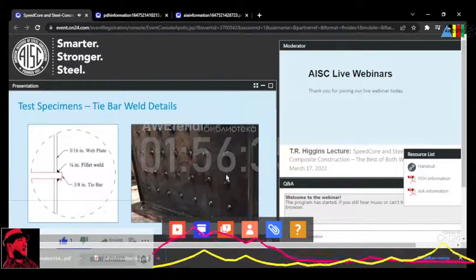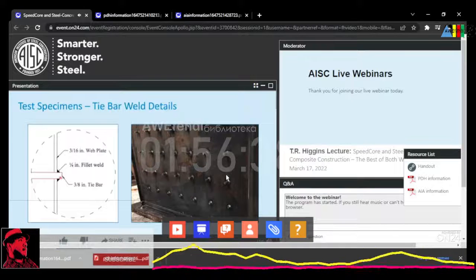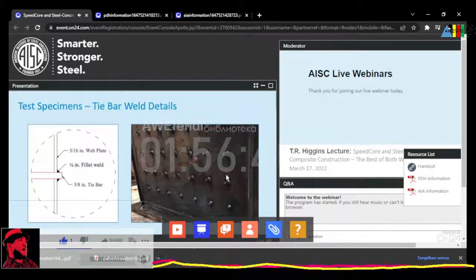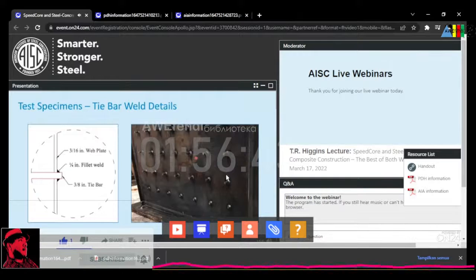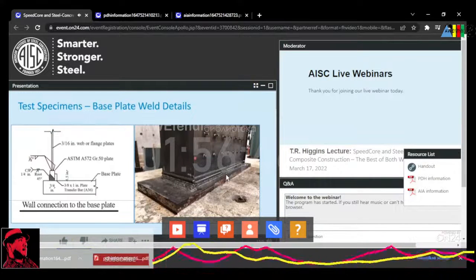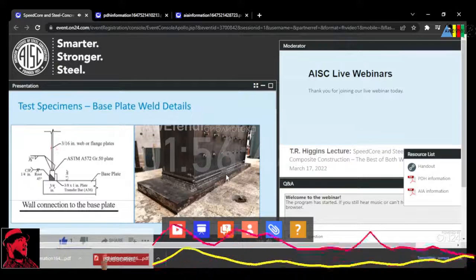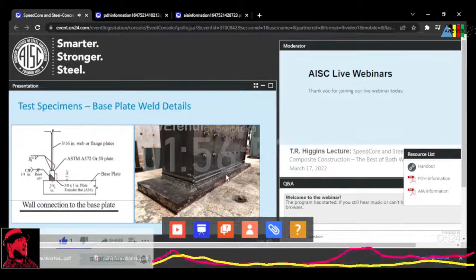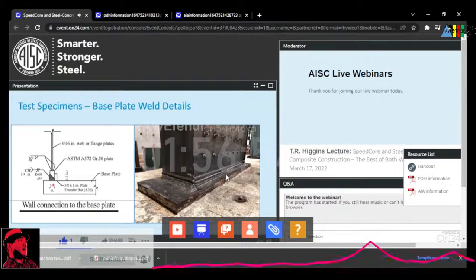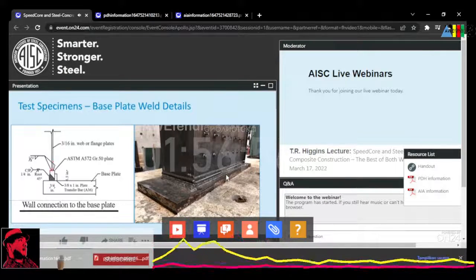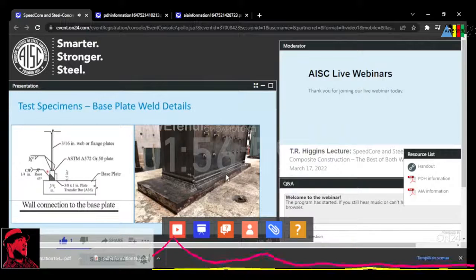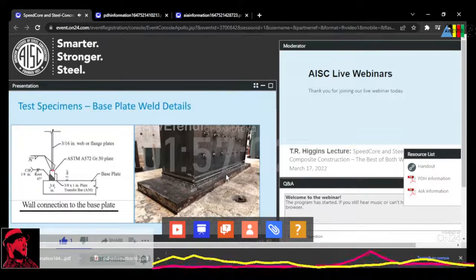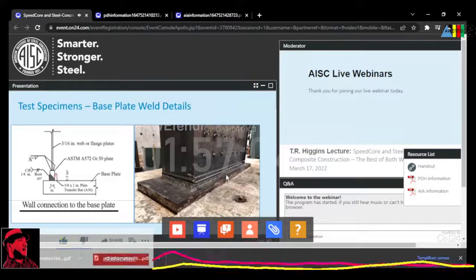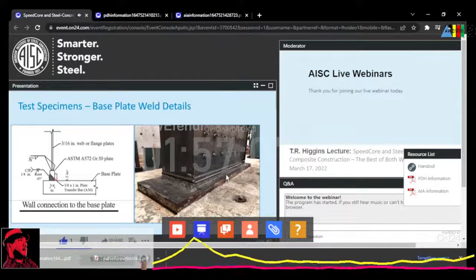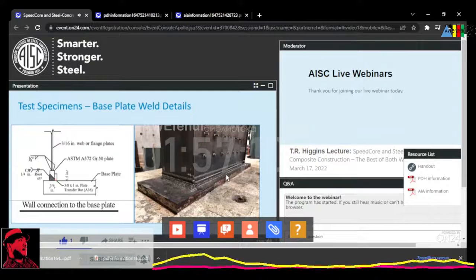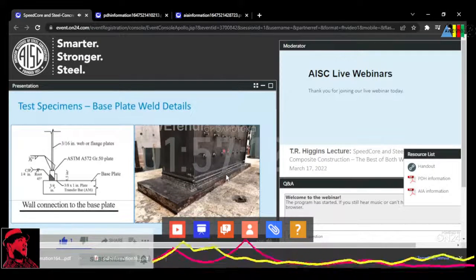The tie bars were fillet welded from the outside, which worked quite well in the specimens and also in the actual structure. A special welded detail was used to connect the 3/16 steel plates to the base plate. The 3/16 plates were fully welded to a 3/4 transfer bar in the shop. The 3/4 transfer bars were CJP welded to the base plate in the field. Now this is only needed for the test specimens because the steel plates were scaled and therefore thinner.